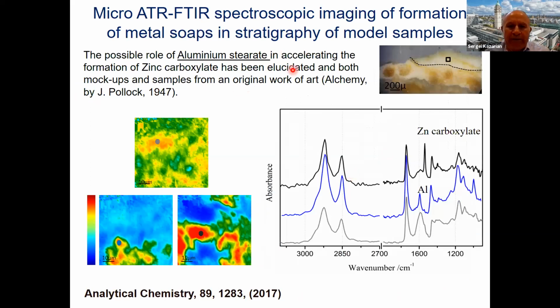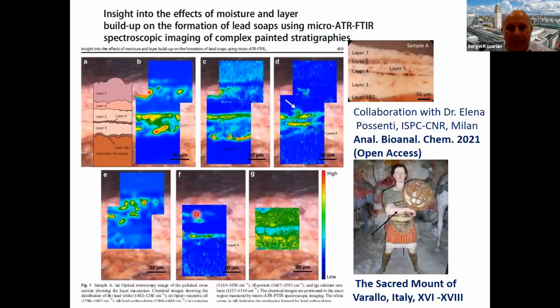The group in Perugia provided model samples, and a student also came here to Imperial College. The model samples were artificially aged by higher temperature or humidity. And in these results, the carboxylate of zinc and the aluminum stearate position very close to these substances was also found in the model samples.